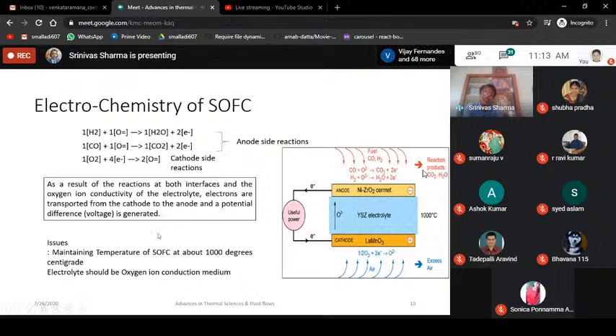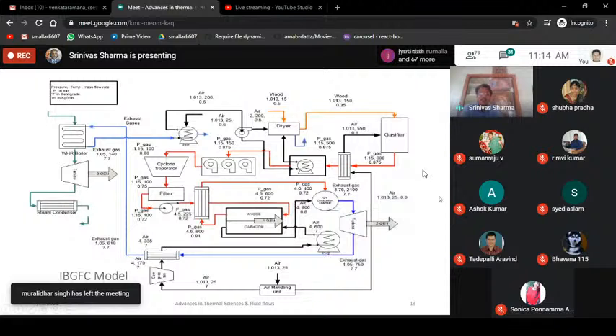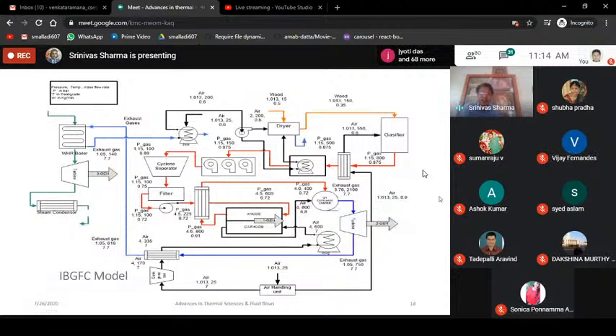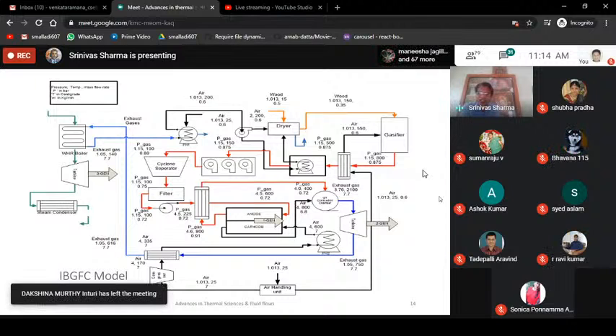So there are issues. The issue is maintaining the temperature of the solid oxide fuel cell at about 1000 degrees centigrade. You have to maintain it with isothermal conditions. Electrolyte should be an oxygen ion conduction medium. That's why we are going for yttria stabilized zirconia. Wherein this is what I have been doing for the last 2 days, sitting and drawing out your IBGFC modules.